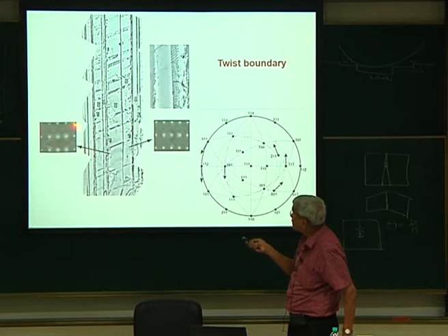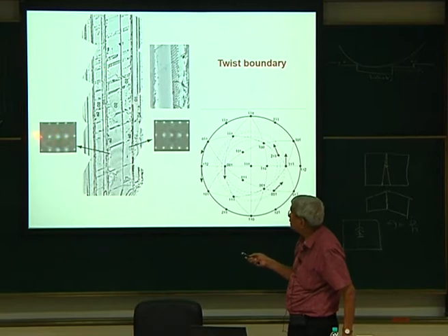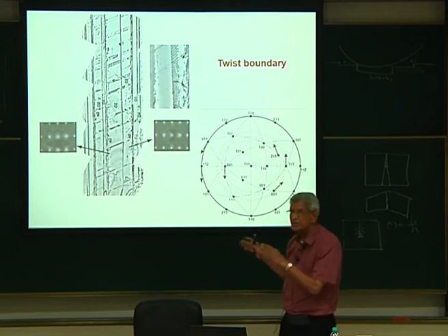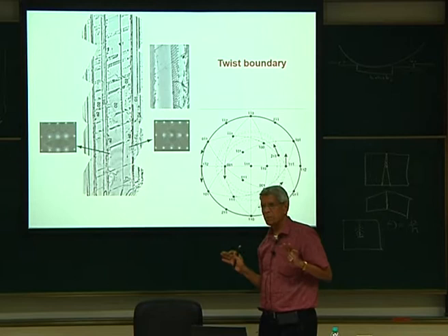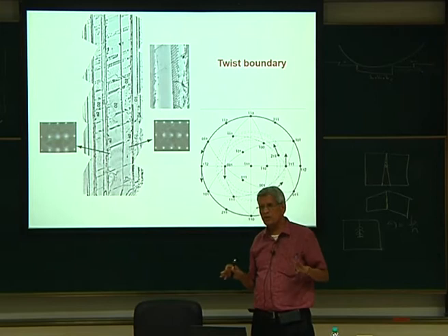And if you see these diffraction patterns which are taken, the spots appear the same in both the cases. But if you look here, you can see some faint background intensity. This faint background intensity, if you see here, is symmetrical with respect to a central spot; here it is shifted slightly away. These are essentially what are called Kikuchi bands. These Kikuchi bands are used to find out the deviation from the exact Bragg condition.